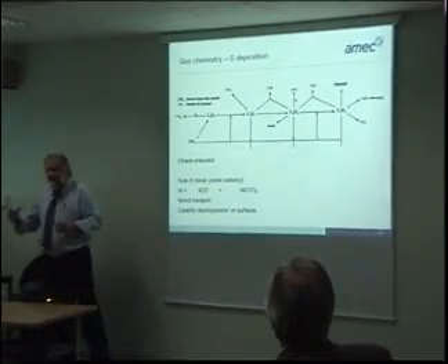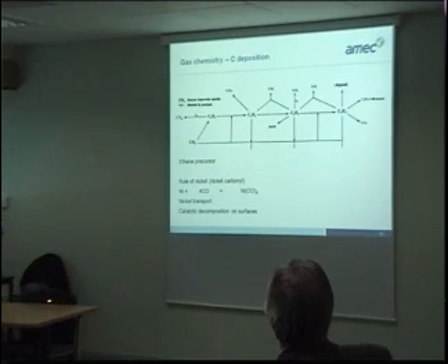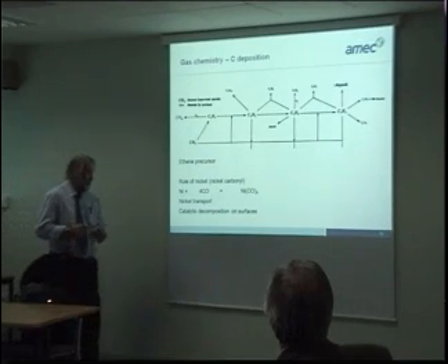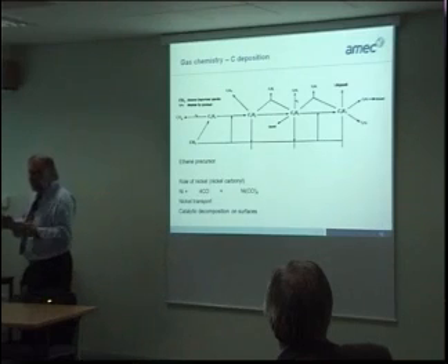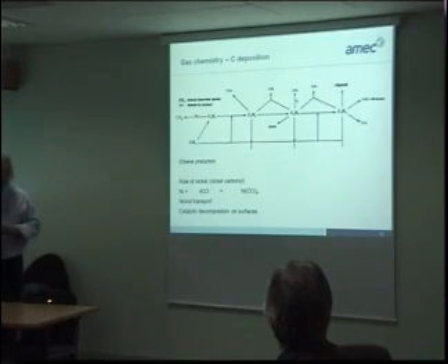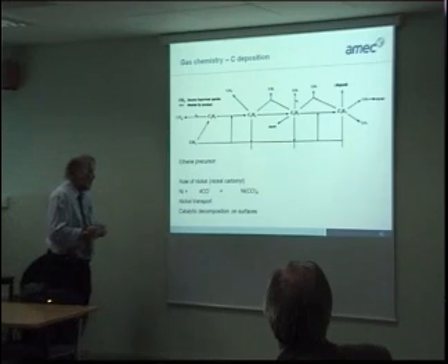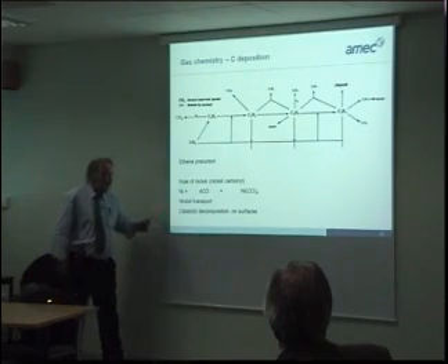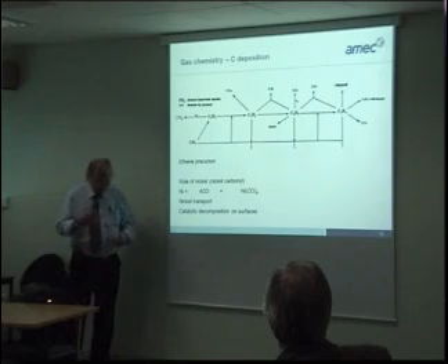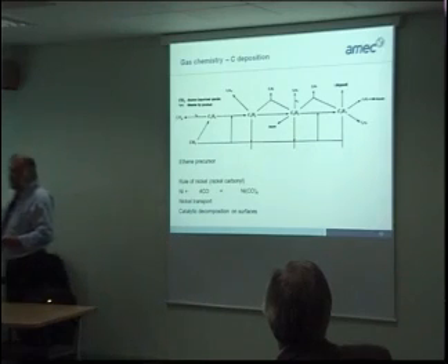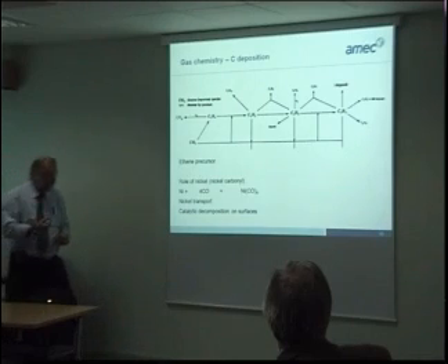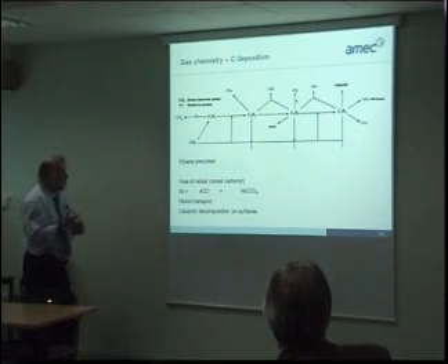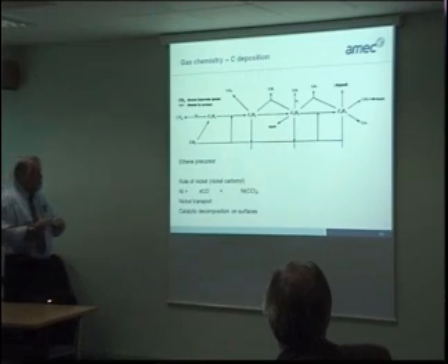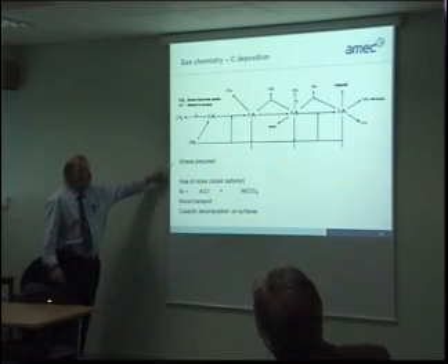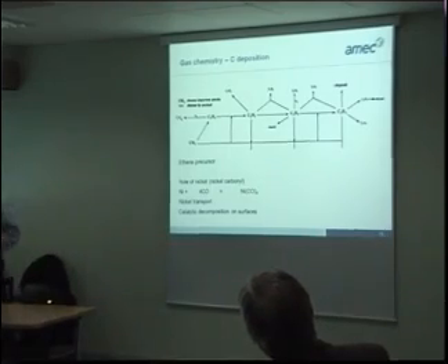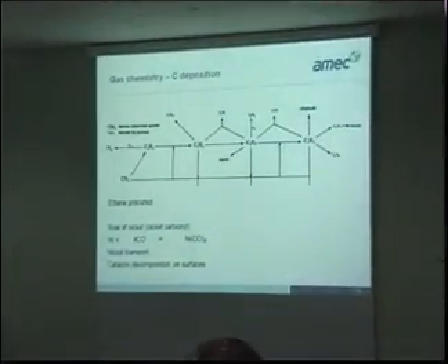So although at high temperatures you'll reach equilibrium faster, the concentration of nickel carbonyl won't be as much. And there's obviously a critical temperature. It's about 200 centigrade where you can maximise the nickel carbonyl concentration. So this leads to a problem on cooler surfaces. The nickel carbonyl decomposes and actually deposits nickel. And nickel is an effective catalyst for carbon deposition with the ethene precursor. So that's the mechanism as understood today.